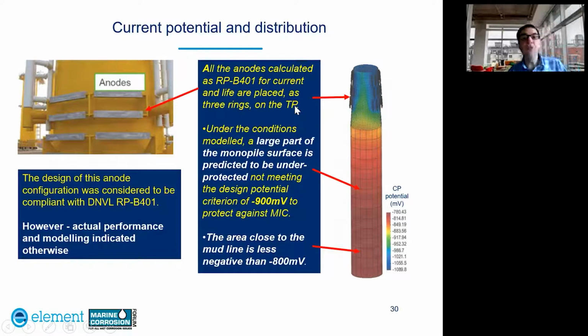So under the conditions modelled, a large part of the monopile structure is predicted to be underprotected, not meeting the design potential criterion of -900 millivolts to protect against corrosion and against microbial induced corrosion, as shown on this model. So also the area close to the mud line is less negative than -800 millivolts. So this would mean it would not be protected against corrosion.